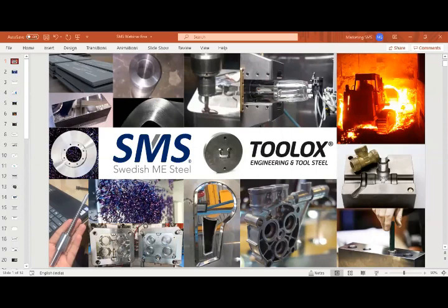Do you have a case study like this? Yes, that's what I shared with you. The one stamping die which I shared was an 8 mm sheet with 800 megapascal tensile strength of the sheet. Previously they were using Vanadis 4E, which is an expensive metal like HSS. But for every 20 to 25,000 shots, they were regrinding it. Though the life of the metal was very high, for every 25,000 shots they needed to regrind it. With Toolox 44 plus laser hardening, even up to 1 lakh shots, they did not require regrinding. So that's where it can help you.